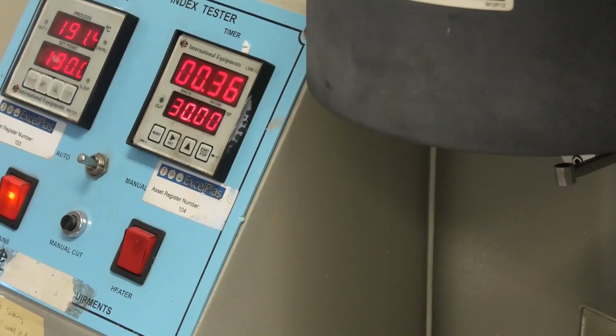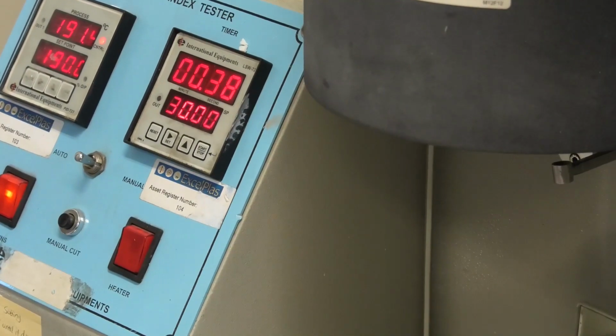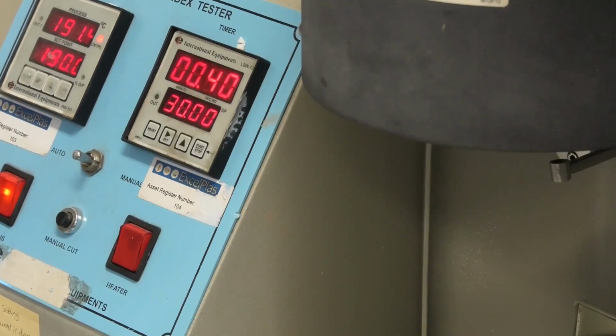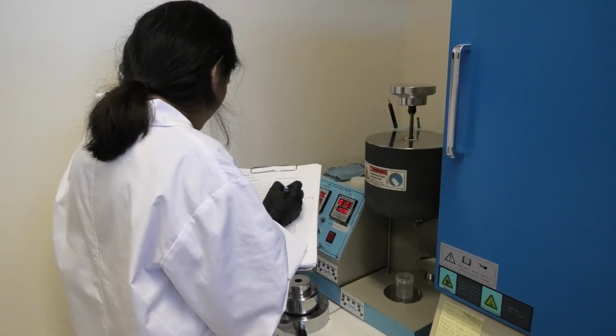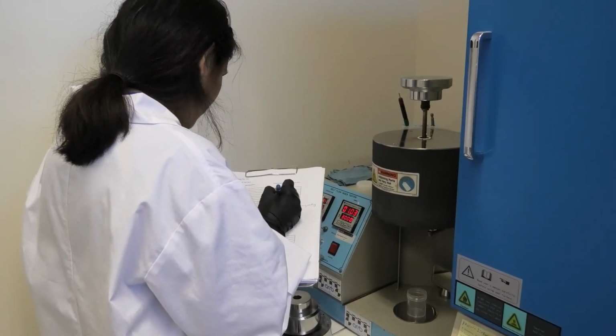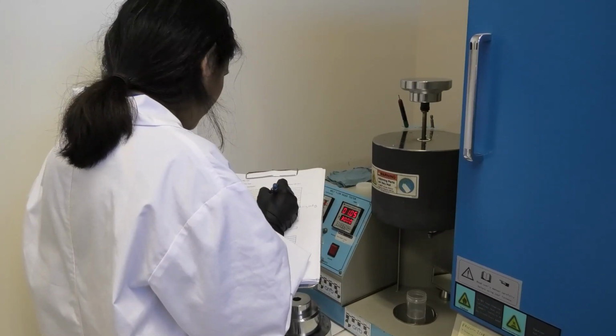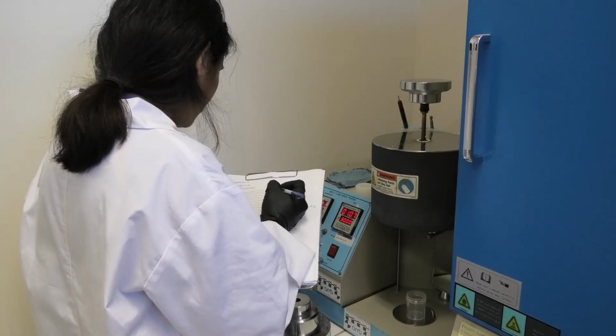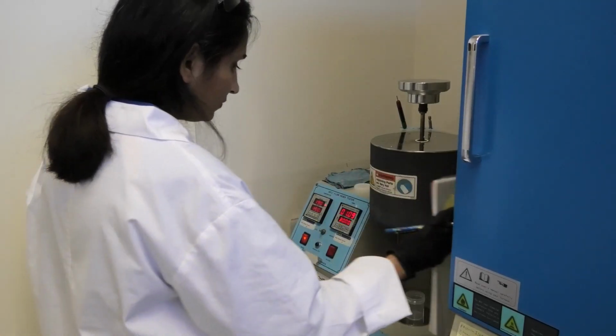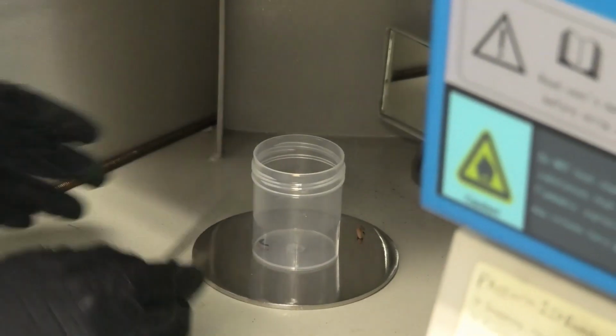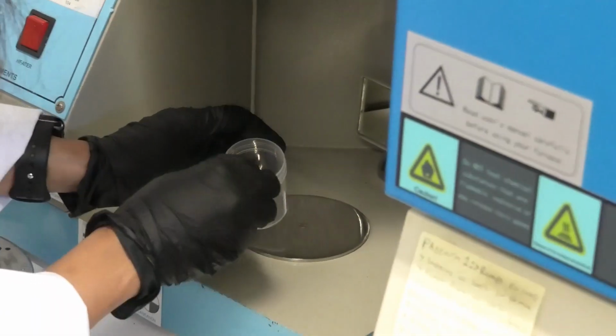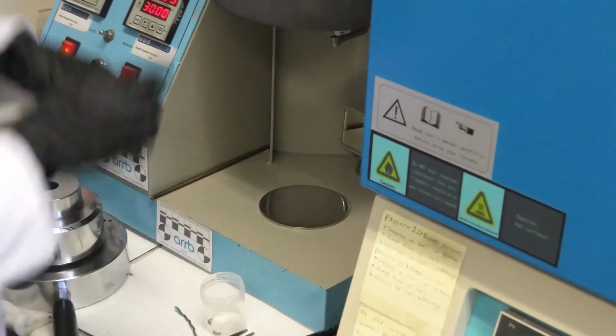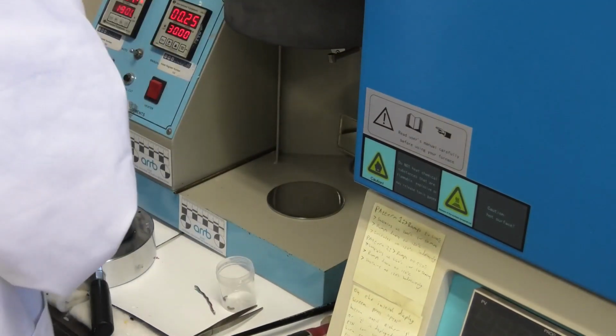And we then determine, by cutting off the extrudate, as it's called, that exits the hole, the mass that actually flows through the orifice in 10 minutes. And that is a measure of the melt viscosity of the material. And it's also a measure; an inverse relationship exists between the MFI and the molecular weight of the polymer.